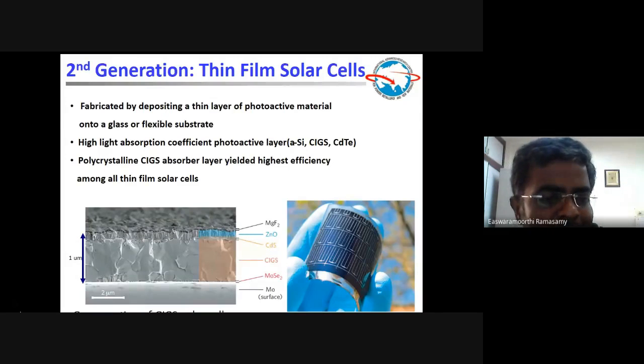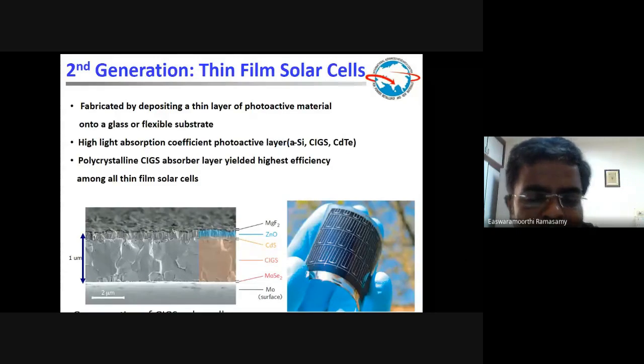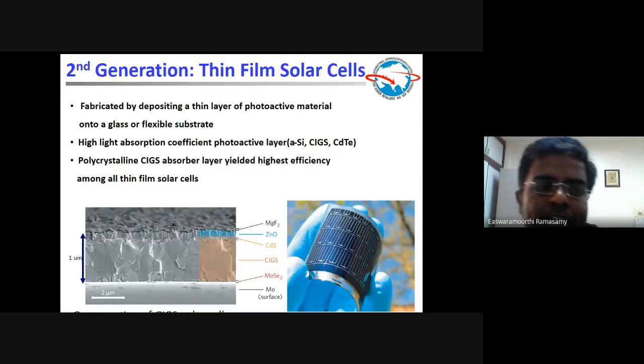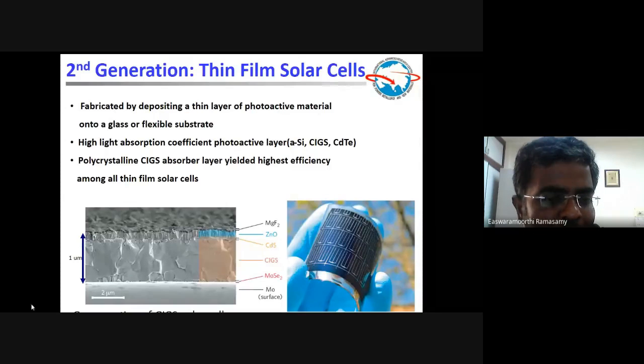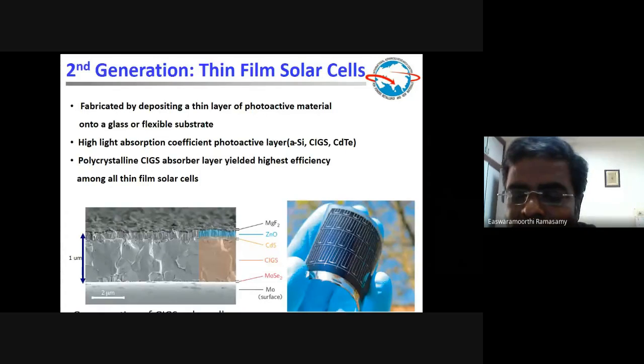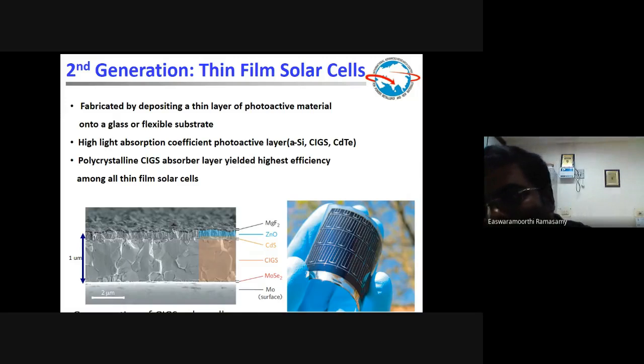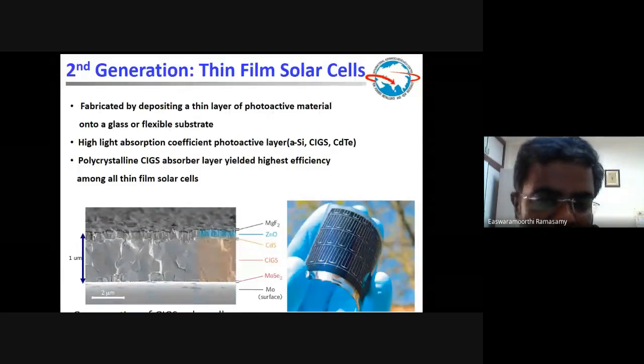Okay, if you reduce this thickness from 300 micron to 1 micron, one aspect is you are using less material, so you can expect some reduction in the cost. But what are the other benefits? If you make the solar cells thin and thin and thin, the first advantage is the cells can be flexible. Silicon is very rigid, it cannot be flexible, but second generation solar cells can be flexible and they are lightweight. So if you take a first generation and a second generation solar cell and compare the weight, they are much less in weight compared with the silicon solar cell.